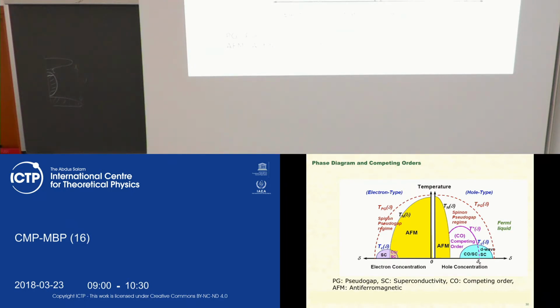So what Anderson says in simple words: when you destroy the antiferromagnetic state by doping the antiferromagnet with holes, what is created is a kind of spin liquid. Spin liquid means that you don't have long range order like an antiferromagnet, but you have short range correlations. And then these short range magnetic correlations can resonate. This resonating state is called RVB, resonating valence bond, and it provides a perfect non-BCS mechanism, by the way, for high temperature superconductivity.